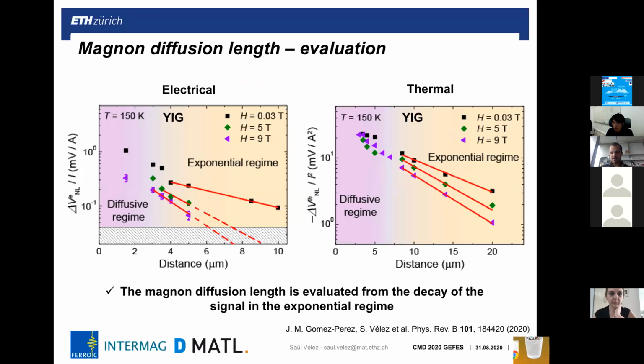Yeah. So the first thing is that for the case of electrical excitation, it's believed to depend on only one decay length. Now there are several papers that show that you have two decay lengths for the thermal excitation. What is known is that the high frequency magnons decay quickly to the low frequency magnons because they propagate much less. But what we infer from these measurements is that we could excite a different distribution of magnons depending on whether we excite the system by spin torque, so electrical means, or thermally. That's what we concluded with these experiments.